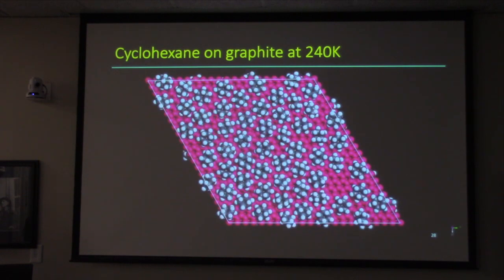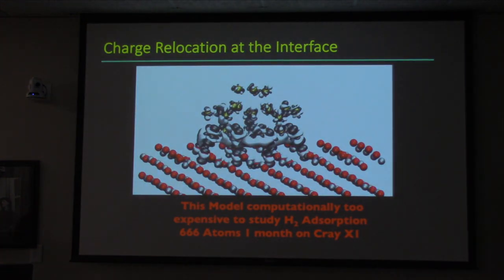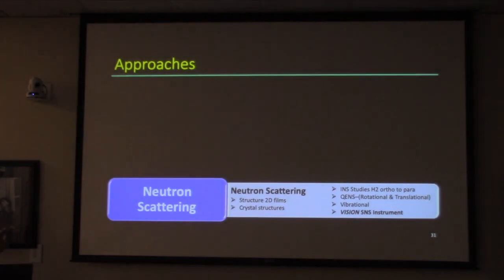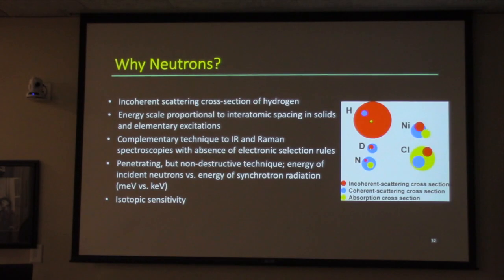We've studied that. Okay, right now I'm just in the home stretch. We did some nice work with Bob Sumpner and a postdoc that we employed to look at this charge relocation. I told you about this. This is palladium decorated zinc oxide, so I'm back to that red and blue picture. This is what you can do with high quality electronic structure calculations. You'll notice that there's a lot of charge distribution. That's what these globs are, if you like, of the electronic charge near the surface. That's very different from this behavior on graphite, where it's really located around the metal palladium. So that's all you get for that. So here's the neutron part.